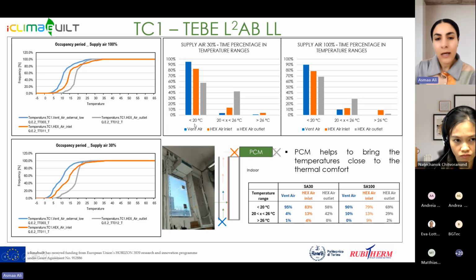So, for example, the PCM was able to reduce the times when the temperature is less than 20 and increase the time and percentage of time when the temperature was between 20 and 26, and also reduced the time percentage when the temperature was more than 26 degrees.